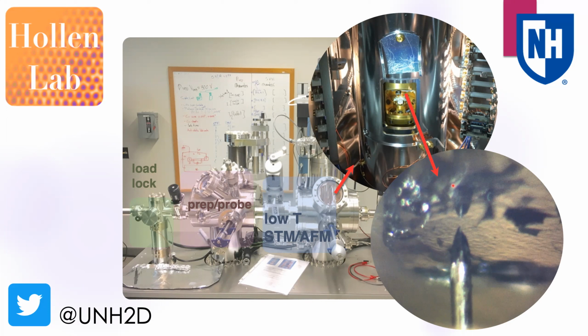Okay. And then kind of going along with what we see in those images, is the lack of atoms in the images a defect or that they have moved? Both. It could be that they were never there and that's how the crystal grew. It formed without that atom there. That's possible. It could also be that something knocked it out. And sometimes we knock the atoms out ourselves. You can create defects with the STM tip. So it could be multiple things. And sometimes we do chemistry on the surface, which pulls the atoms off of the surface, so that we've created vacancies that way.